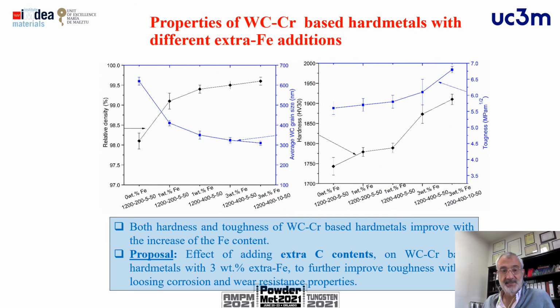Here we have some of the results regarding the relative density and the average tungsten carbide grain size. Also in this graph on the left, you can see how the grain size decreases with the increase of iron. So it could be a good idea to try to combine the carbon with these high levels of iron. So we have selected 3% of iron, and we mix with this 3% of iron different contents of carbon that we will analyze later.